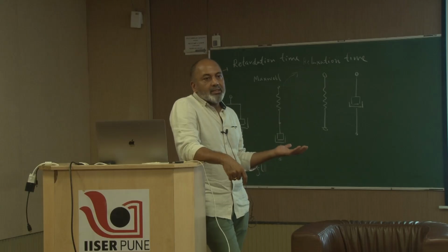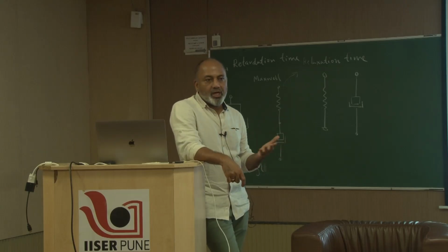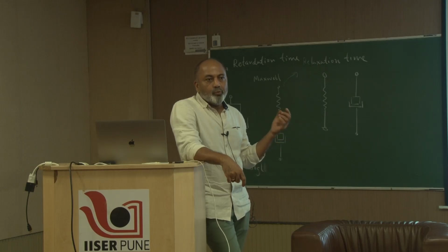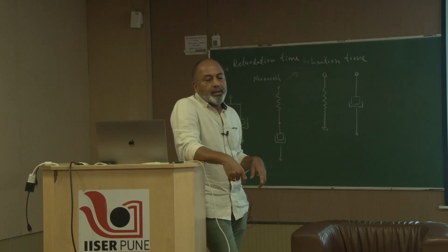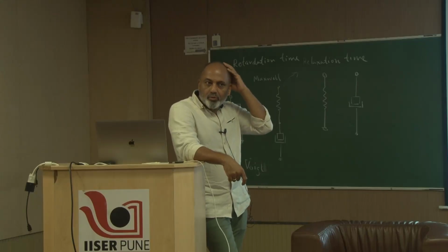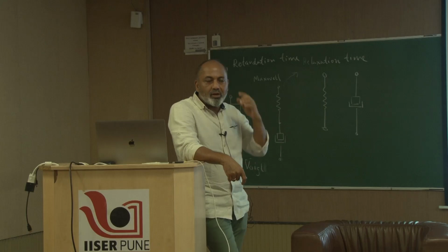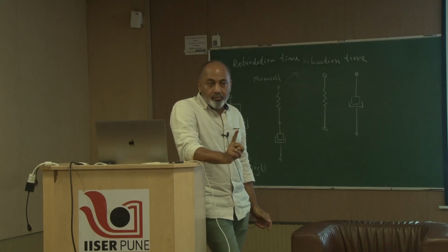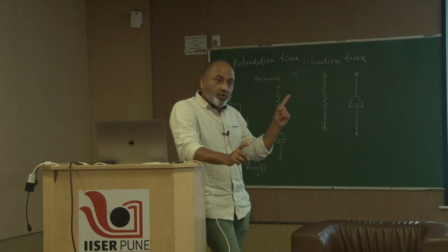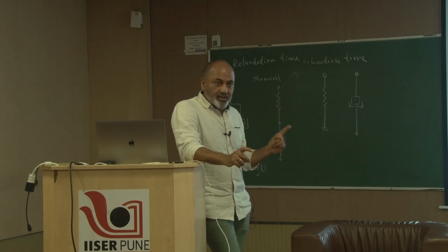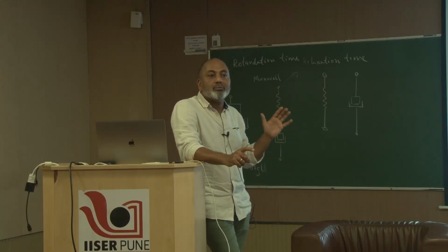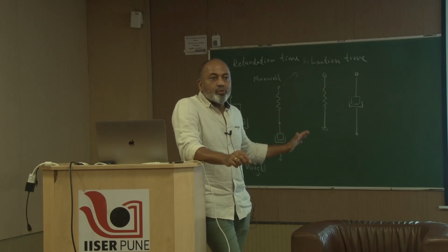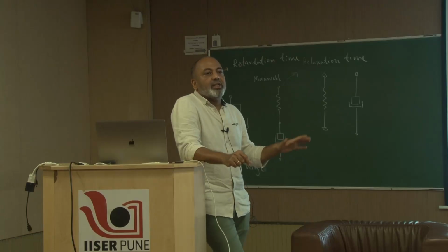So we take glass, and for Nagaraj's work we have an extremely thin layer of collagen with polylysine and things, so that the cells are nicely sitting there without spreading too much. In the case of Deepa's work, we use some other gel, I forgot now which one. But what we did was make a measurement on just that gel, and it should be cross-linked with enough concentration so that when you press on it, it gives you at least some 100 megapascal or so Young's modulus. So when you're pressing on a cell, the gel is not getting compressed.